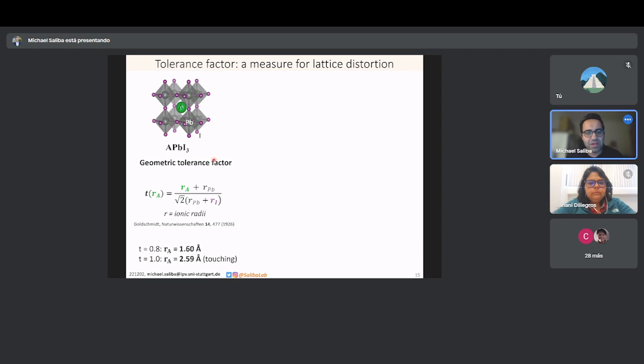And then these octahedra, when put together, leave a gap, the cation gap. And this cation doesn't interact much with the metal halides, which is very interesting. There's a little bit of interaction, but it means essentially you need something in this gap so that the metal halide octahedra don't collapse. And when you make it too big, there is no more space. When you make it too small, there is too much space. So you need to have the right situation.